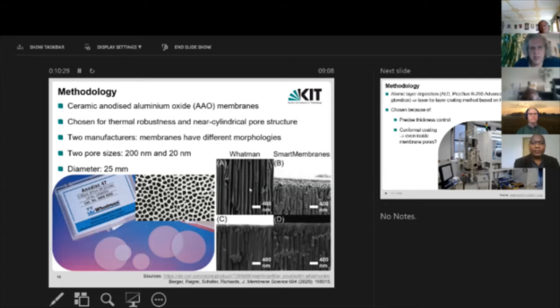So probably clearest shown on the top left SEM image, where in the cross section you can see somewhat defected but quite nice pores running up and down the edge of this membrane. We chose to investigate two different membranes. So we bought membranes from Whatman and also a German company called Smart Membranes. And these were given also in two different sizes. So we have 200 nanometer diameter pores and 20 nanometer diameter pores. And I think I forgot to mention before, the membranes are 25 millimeters in diameter when they fit inside that cell, and 60 microns in thickness.